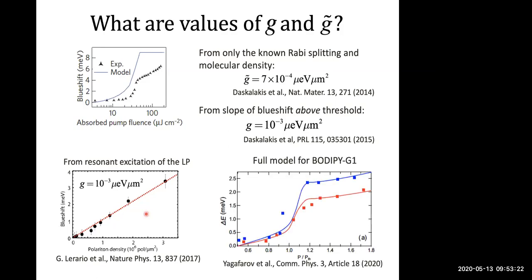Very recently, there was a nice paper by the group of Pavlos Lagoudakis, where they carefully measured the blue shift as a function of pump power, and modeled this by not only accounting for a single reservoir, but also accounting for the fact that you have molecules with a transition dipole moment which is misaligned with the polarization of the condensate, and accounting for energy transfer between the different possible states. And this model accounts now very nicely quantitatively for the blue shift as a function of pump power, and also directly gives you the spontaneous polarization of the condensate as a function of pump power.